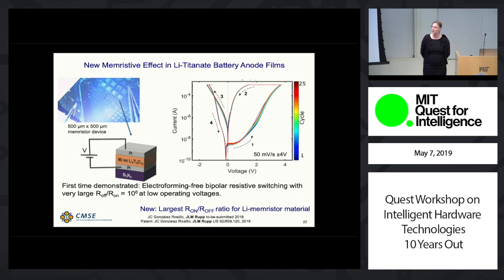It's a thin film structure and architecture. Currently we test on 400 nanometer thin films, right? So we haven't scaled it further down, but there's actually potential, as long as you can keep the stoichiometries well controlled in processing, to keep that architecture also at much smaller thicknesses.